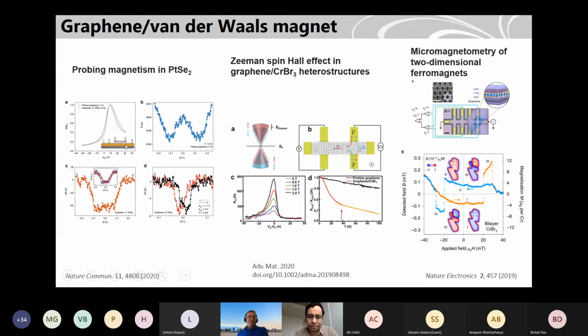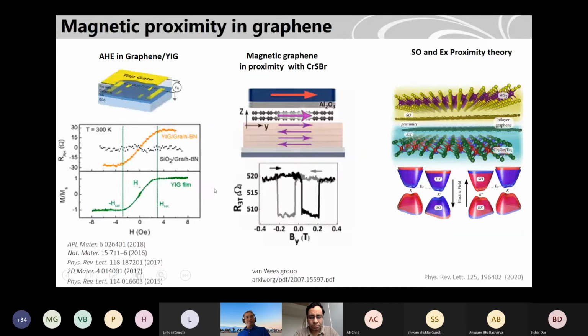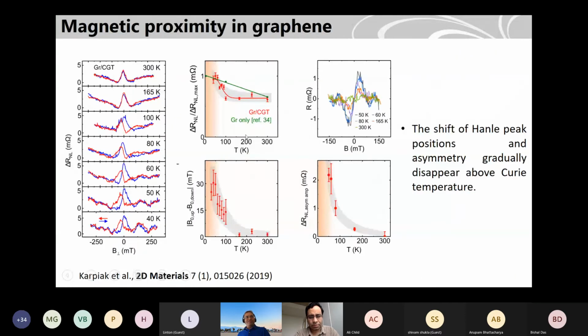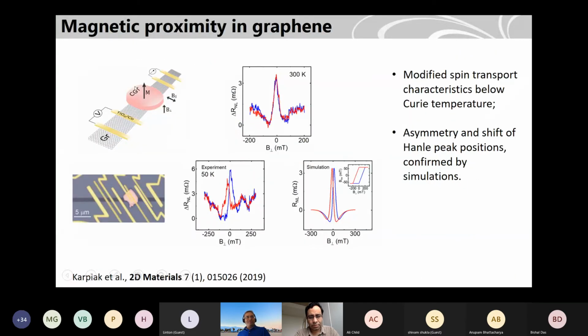Here also, with graphene on platinum selenide, they detect the magnetism of platinum selenide with graphene. And similarly, what we do is, with such a structure, the magnetization and proximity effect can be detected by graphene.